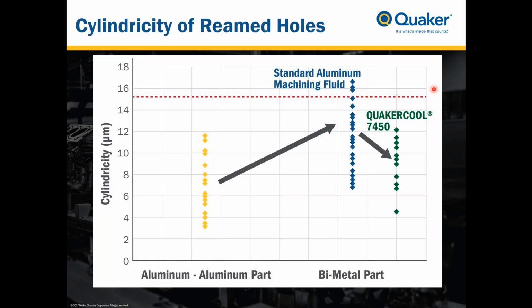And when we use QUAKERCOOL 7450 in this operation, we see a noticeable improvement in the cylindricity obtained with the cast aluminum powdered metal part. This is significant because it's a noticeable difference, and actually it gives cylindricity results that are very close and comparable to those that you would get with an aluminum part.